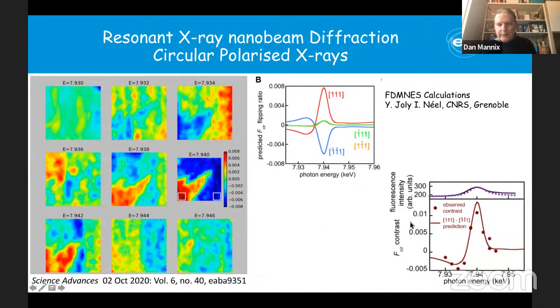From that, we can also make a predicted contrast, and that's what we've shown here. This is the measured contrast, obtained by measuring these different regions as a function of energy. That also agrees very well with our prediction from FDMNES.